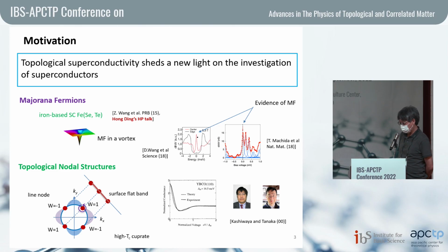in the vortex. And here I show the related STM data, and this is the Chinese data, and this is the Japanese data. As you can see, both data clearly show the presence of the zero bias peak coming from, probably, the Majorana zero mode in the vortex. And in particular, in the right picture, you can see the zero bias peak well separated from the peak coming from the mini-gap state of the vortex state. So this zero bias peak should be a strong evidence of the presence of the Majorana zero